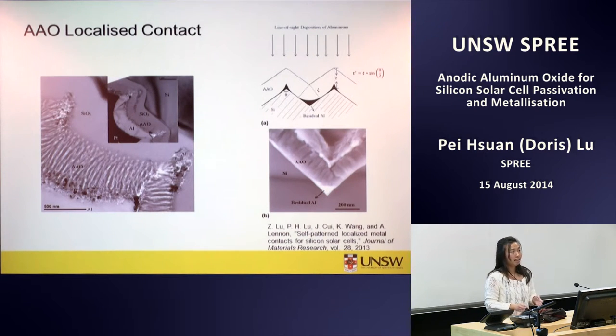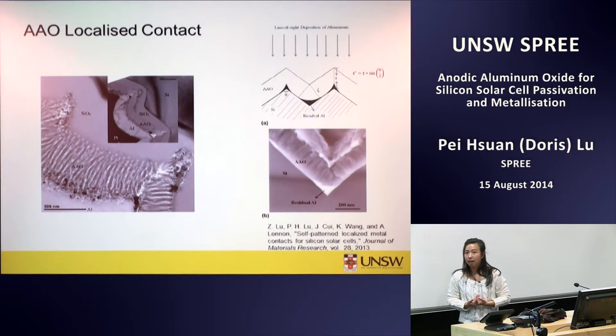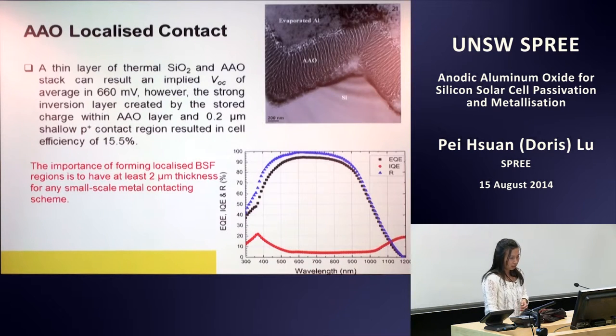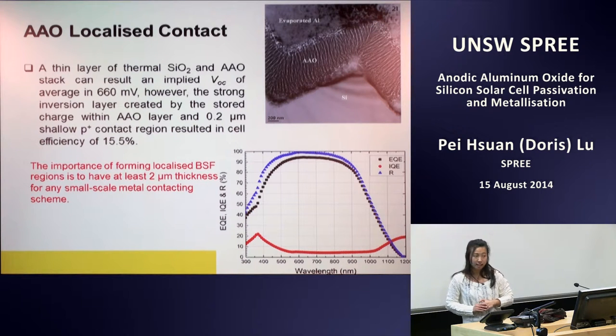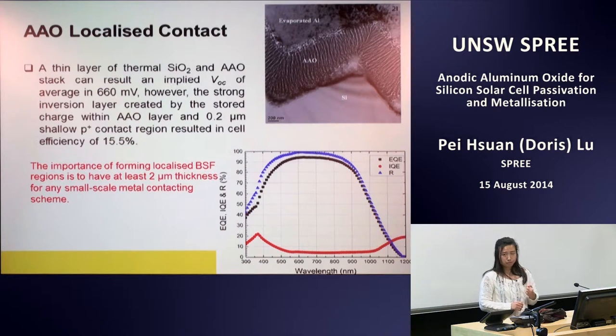And later, John Lu found out that at the peak or valley of a pyramid, there is a residue of aluminium that didn't get completely anodized during anodization. Later, during the firing, it fires through the thin silicon dioxide and makes a contact with the aluminium. However, a thin layer of anodized aluminium on top of the silicon dioxide can improve implied VOC up to 660 millivolt from 600 millivolt. The strong inversion layer is created by the stored charge within the AAO layer, and also this residue aluminium can